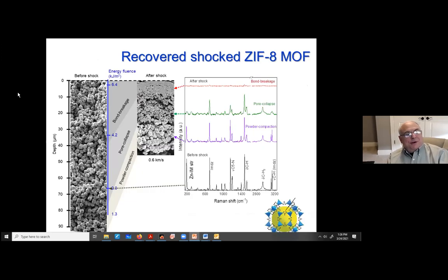So here it is in more graphic form, okay? This is what the sample looked like before anything happened. It was a column 90 microns thick of this powder. Then the flyer plate comes in up here, wham, and it's compressing. We took it over to our MRL, and this is what it looked like. I took off a big piece of aluminum that was stuck on it, which I'm not showing. The flyer plate hits here, so the shock is very big here, and as it moves through, it gets attenuated. This one snapshot shows you material shocked very hard, medium hard, and not so hard.